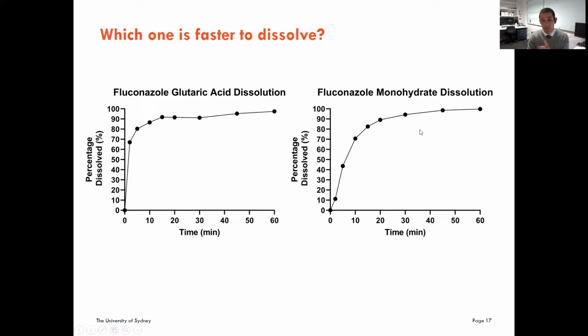When we compare that to the monohydrate form, at 2 minutes, we had just over 10%. That's quite a considerable difference in terms of speeding up that dissolution, which means we can get more medication into the body at a faster rate, which is a very, very promising result. When we look at the 10-minute mark, our co-crystal is almost at 90%, whereas the monohydrate has only just reached 70%. For the monohydrate to reach 90%, it took about 20 minutes, whereas our co-crystal took only 10. So doubling the speed of dissolution was very, very good news to reaffirm a lot of the theoretical studies we've done based on the structure.